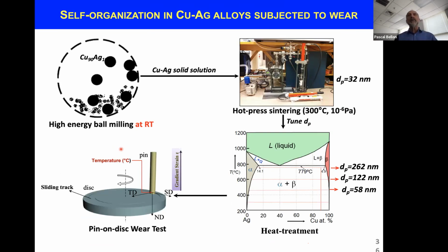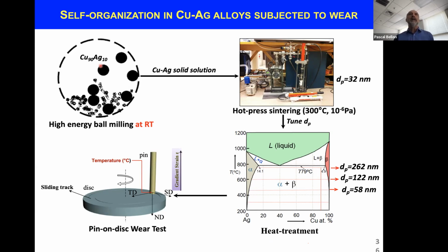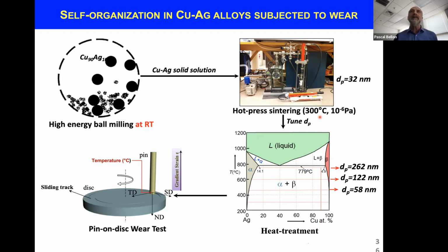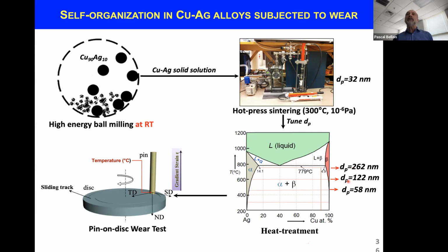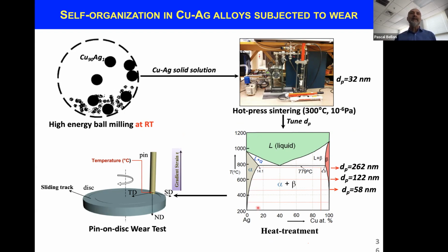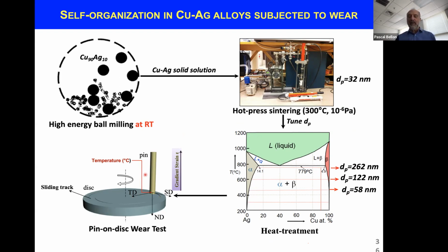And the last example I would quickly want to show you is going back to this copper silver system. It's a case where we have 10% silver in copper. It forms a solid solution if we ball mill at room temperature. And then, after compaction and sintering, we anneal this material at different temperatures to reprecipitate the silver. By choosing the annealing temperature for 1 hour, we can choose different precipitate sizes. And we tested these nanocomposites on their sliding wear using a pin-on-disc wear tester.